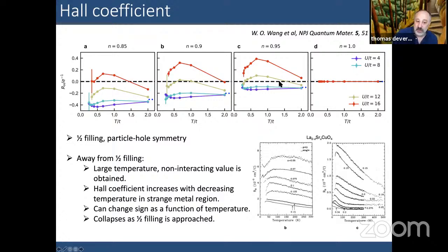It can change sign not just once, but twice, as it does here for U of 12 at 5% doping or here at 10% doping for U of 12. And of course, at large temperature, the Hall coefficient doesn't know about the correlations. So that's this dotted line here, where the non-interacting value is obtained, and then generally it tends to increase if U is bigger than 4, going off of the non-interacting value. And as I said, it can even change sign. And for our case, it collapses as you go to half filling because we don't have T prime turned on.